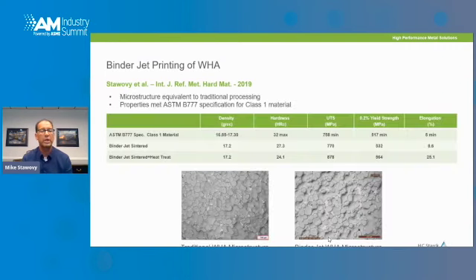If we then compare the traditional tungsten heavy alloy to a binder jet printed tungsten heavy alloy, you can see in the microstructures at the bottom of the slide that there's no visible difference between a traditional powder metallurgy tungsten heavy alloy microstructure and one that's been binder jet printed and sintered. And we've also met the ASTM specification for tungsten heavy alloy, which is ASTM B777. That's shown in the table.